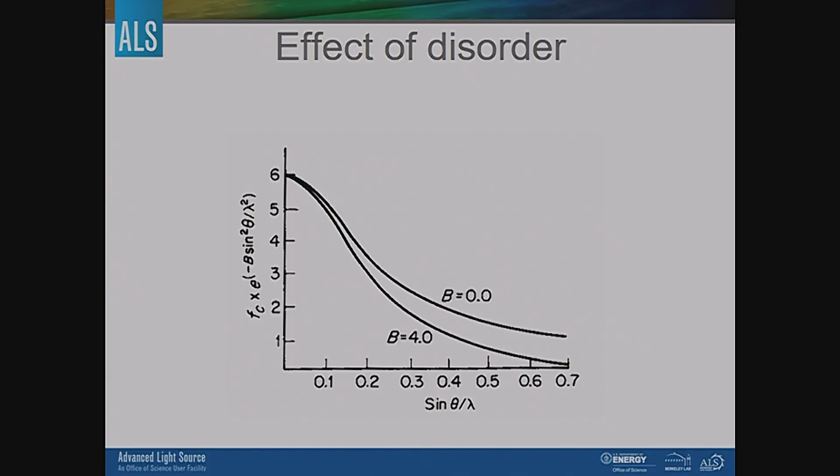So when we talk about B values, that's the old school version of U values, which we consider thermal parameters. So if your thermal parameter is perfect, then this carbon atom will scatter out to really high resolution. The second you add on some thermal parameter wiggle, it drops off. And eventually it actually goes to 0. Once that goes to 0, it doesn't matter how hot your synchrotron source is. There's no there there. There's nothing left. It is waggling to the point that it can't be relied on for any kind of interference.